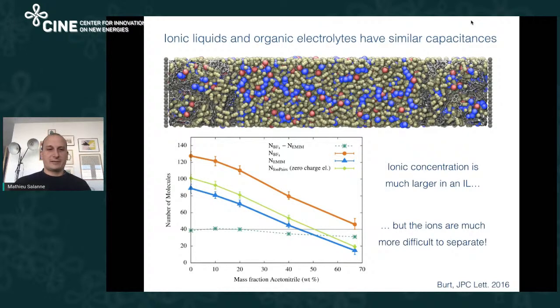It's the fact that when you increase the content of acetonitrile, you decrease a lot the number of ion pairs. You switch from 100 in that example to 20. So you divide by 5 the number of ions inside the pores. So you could expect to divide by 5 the capacitance. But in fact, the important thing is not the number of ions inside.